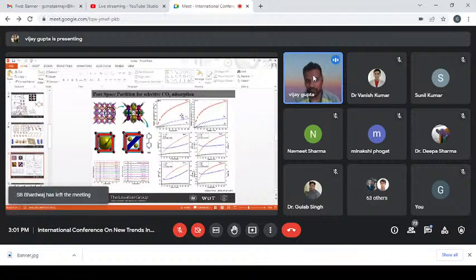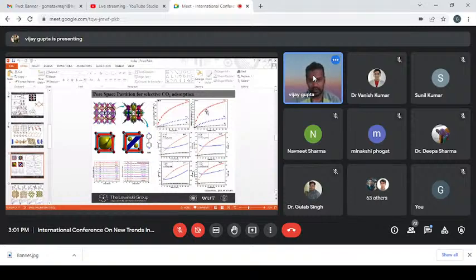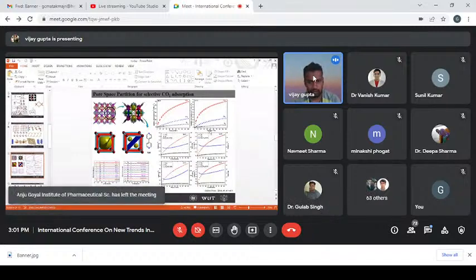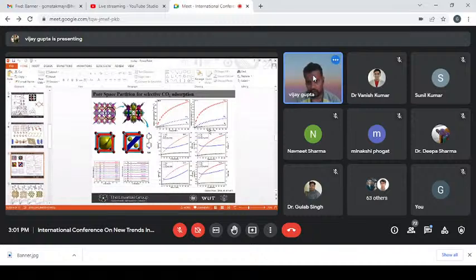And here you can see the adsorption data at 298 and 273 K, because when we talk about CO2 adsorption, we have to deal with higher temperatures. People do adsorption at low temperature, but whenever you publish a paper on CO2 adsorption, reviewers will definitely ask what the adsorption profile is at higher temperatures. We can see that at both temperatures, nitrogen and methane adsorption is very low compared to CO2. And we calculated these selectivity numbers because we don't have the facilities to conduct mixed gas adsorption.